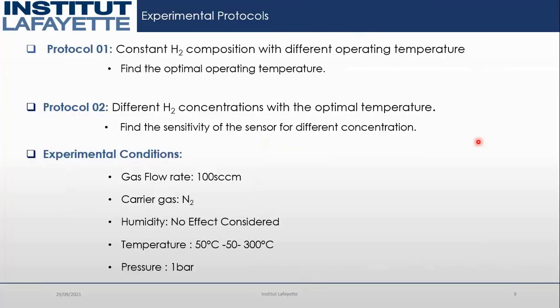For this work, we ran two experiments. The first one, we varied the operating temperature from 50 to 300 and kept the hydrogen concentration constant at 10,000 ppm to find out a suitable operating temperature for our application. The second one, we varied the hydrogen concentration from 1,000 ppm to 10,000 ppm and kept the operating temperature constant to verify the detection of hydrogen gas using the ITO HEMT. In both experiments, we kept the flow rate at 100 SCCM and considered no effect of humidity.